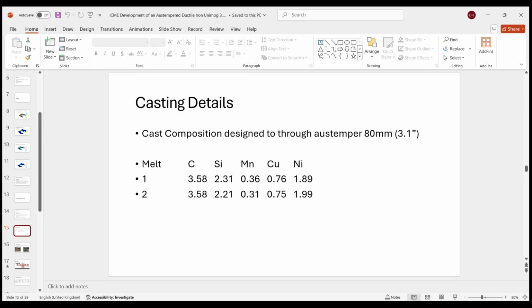That gives us a margin of safety, so that when we quench the component, the surface and the core will transform into the correct microstructure at the selected austempering temperature. The way we do that is by adding hardenability agents. Carbon itself obviously offers the greatest hardenability factor. So with steels, which normally have lower carbon, you can only through-austemper very small sections, whereas with irons you can through-austemper heavy sections, because you've got a lot of carbon in the matrix.